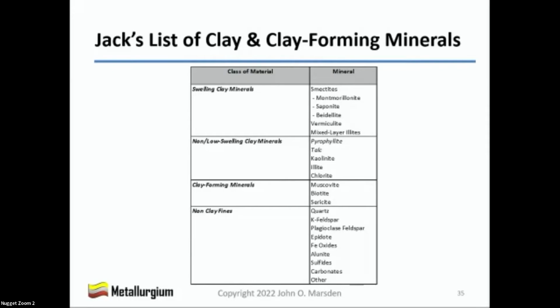True, said Diane, but you can also use a near-infrared instrument to estimate swelling clay and non-swelling clay content, as long as it's calibrated against quantitative cation exchange capacity, or CEC, and XRD measurements on a representative set of samples from the deposit. She carried on. The NIR instrument is inexpensive to buy. It performs the analysis very quickly, and it is simple to run. Any lab tech can be trained to run it. Next slide.